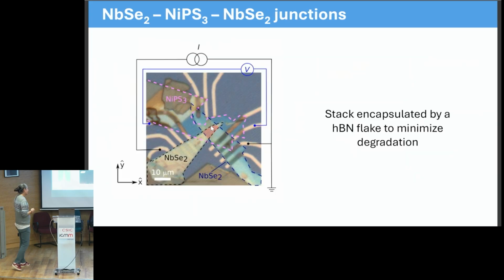So moving back to our device. This is how it really looks in an optical microscope. We have these three sandwiched layers, and the Josephson junction forms where the three layers intersect, which I'm highlighting here in red. And to prevent further degradation of the materials, we encapsulate the whole thing with a top hBN layer.